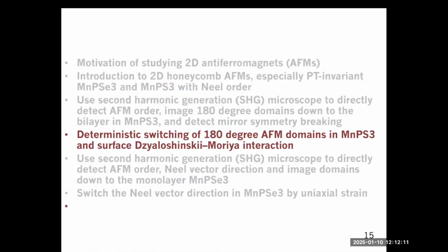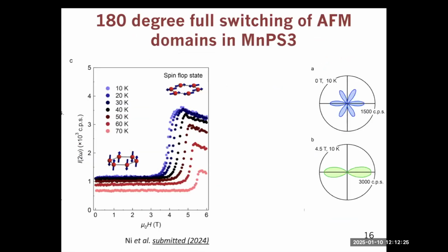So we don't know. So now let me show you the unexpected discovery in this compound, which is the 180 degree domain switching by the magnetic field. Okay, because usually for a magnetoelectric, you have to apply E and B. But we are applying B out of plane, in other words, parallel with the E field, which is forbidden from the magnetic group symmetry. So here we basically measure second harmonic generation as a function of out-of-plane magnetic field. Okay, on the C star axis, you can see that. So this is a spin flop. When the signal changes here, this is the spin flop.